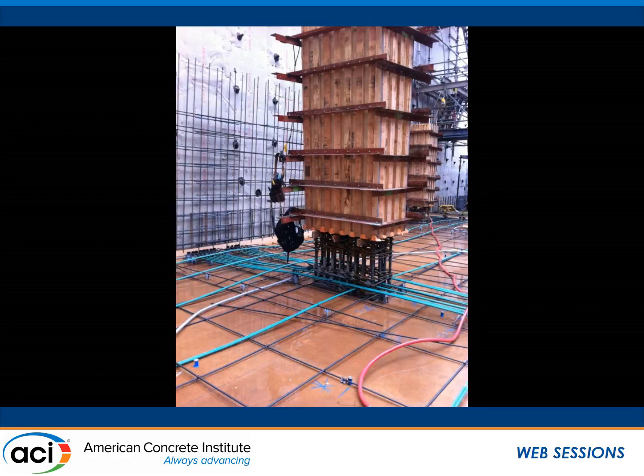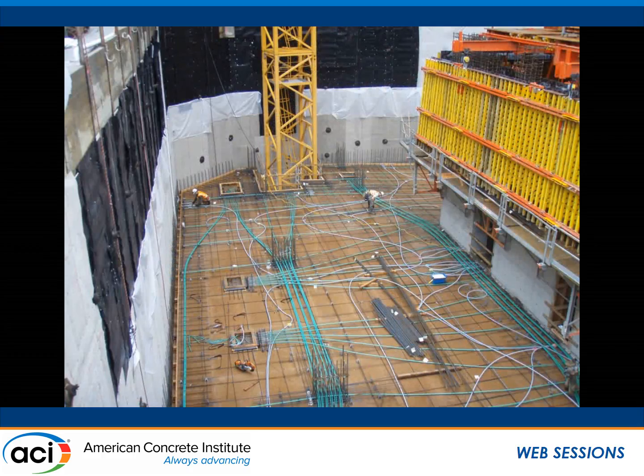The PT, at the lower levels, was stressed internally, and the closure pours that were created for the PT, you can see we had pockets in the banded direction, and we'll have a closure pour in the distributed direction on this side that you can't see on this shot. But they were poured immediately after stressing and capping the tendon, so you didn't have to wait 28 days. So the formwork was still there below grade, and then you just pour these closure pours.